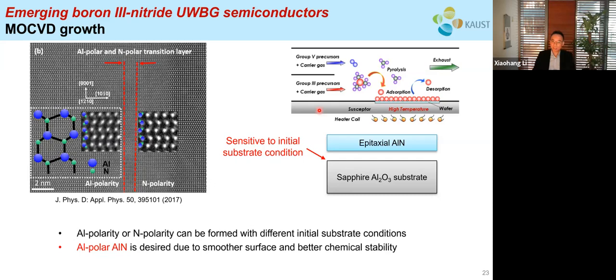And to grow aluminum nitride by MOCVD, because it's a chemical process, the growth is very sensitive to the initial substrate condition of the sapphire substrate. This image here shows the high resolution TEM image taken by my group down in the KAUST core lab, showing two kinds of polarities of aluminum nitride grown by MOCVD on sapphire. This difference in polarity is due to the initial substrate conditions. Ideally, we want only one polarity, especially the aluminum polarity, because aluminum polar aluminum nitride has a smoother surface and better chemical stability. But without a proper surface treatment, you will end up with both aluminum polarity and nitrogen polarity. And this is not ideal for device applications.